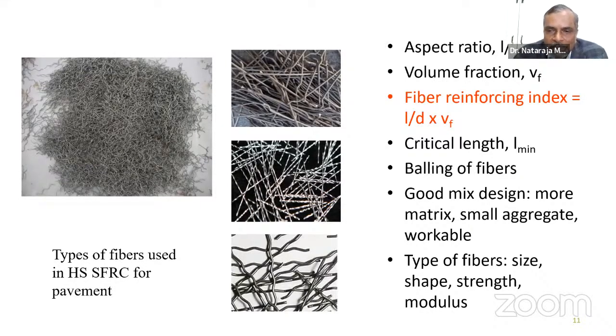So that is where selecting a certain minimum length, depending on the size of the aggregate, plays a very important role. Any fiber in excess of about 2%, we have the balling problem, and we need to go for good concrete mix design. Many such things come into the picture, because in the current IRC, fibers are permitted unless you know many of these things, mainly from the point of mix design. Producing a very good steel fiber reinforced concrete may not be that easy.